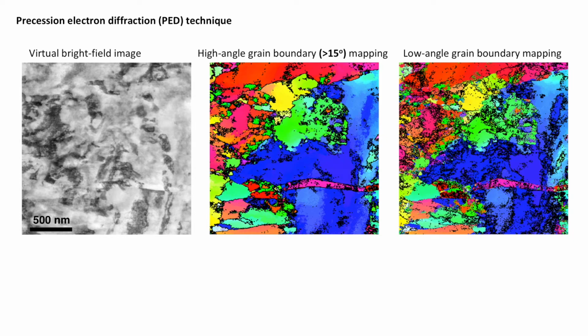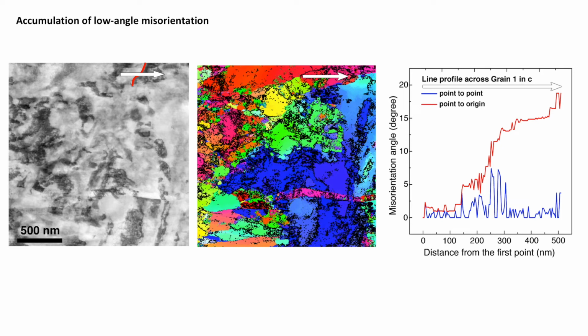One may argue that if we are only getting a lot of low-angle grain boundaries, why do we see diffraction rings, which seem to be continuous, covering a large range of crystal orientations? To address the question, we drew a line in the shear band to look at both the point-to-point misorientation and point-to-origin misorientation. The blue line depicts the point-to-point misorientation. For point-to-point misorientation, the difference does not change dramatically. Maximum is only 5 or 7 degrees. But the small point-to-point differences can accumulate and lead to a large point-to-origin difference, as shown by this red curve here. Only about 500 nanometers away from the origin, and you already see the accumulative effect of 20 degrees misorientation. This is why in the diffraction pattern we see the ring patterns.